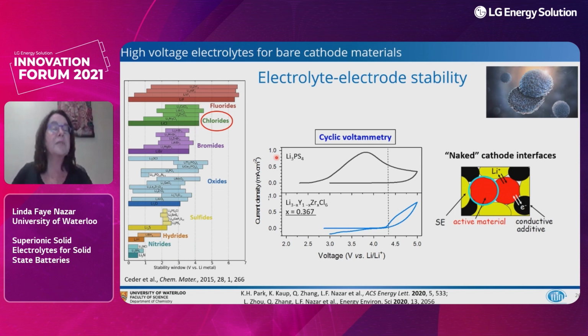And that's effectively what we see by cyclic voltammetry. And these are kind of the worst case scenario experiments because we mix the halide with a lot of conductive carbon to see what its stability is. So you can see, we compare here Li3PS4 with a mixed metal halide that we developed. I'll talk about that in the next slide. And you can see that the onset of oxidation is pretty much where it's predicted, 4.2, 4.25 volts, whereas that of the Li3PS4 starts at just about 2.5 volts.